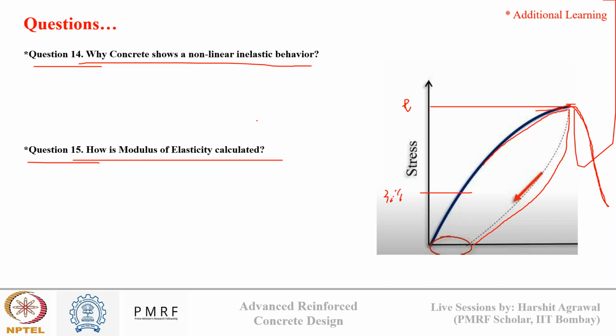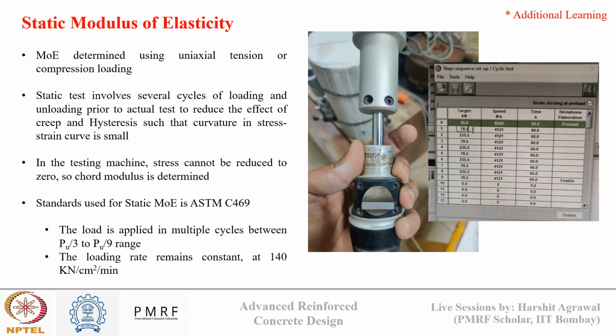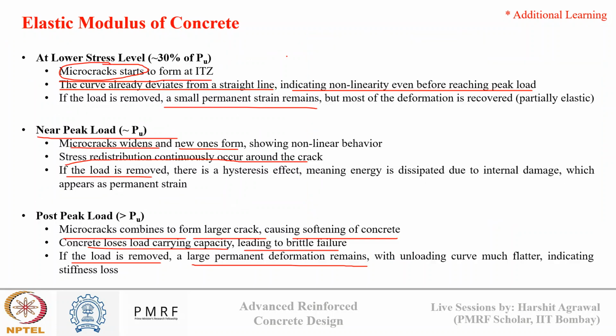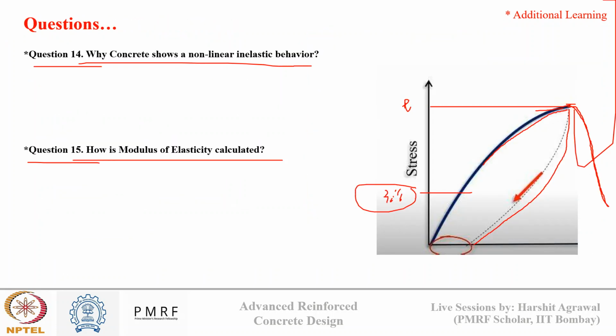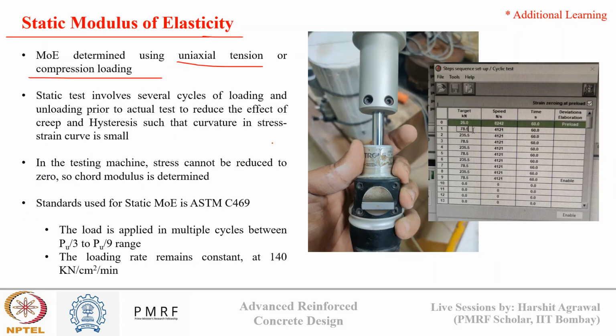Now, how is modulus of elasticity calculated? Basically in the lab, we use uniaxial tension or compression loading to calculate modulus of elasticity. There are two ways in which we can estimate it: static modulus of elasticity and dynamic. Generally for laboratory applications, we use static modulus of elasticity. In this, in the region of 30 to 90% of ultimate load, we subject our concrete to cyclic loading, and then we calculate the modulus of elasticity based on chord modulus.